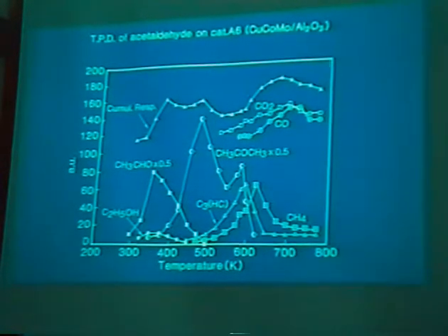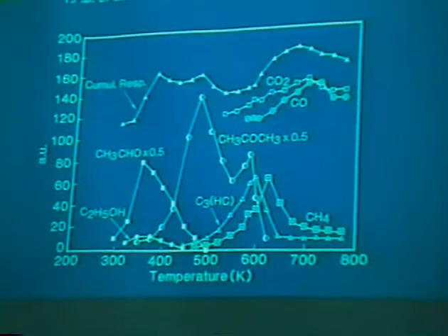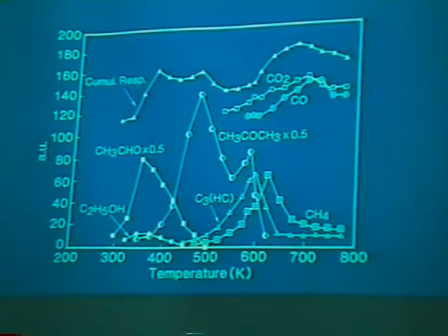So let's look at what occurs when you adsorb acetaldehyde and then make it react by increasing the temperature of your catalyst bed. In these small experiments performed at lab scale on a few milligrams of catalyst, and thanks to online gas chromatography analysis, we were able to detect all these products. So here you have the cumulative response that we obtained on the katharometer versus the temperature. And here you have the detailed analysis we found through online gas chromatographic analysis.